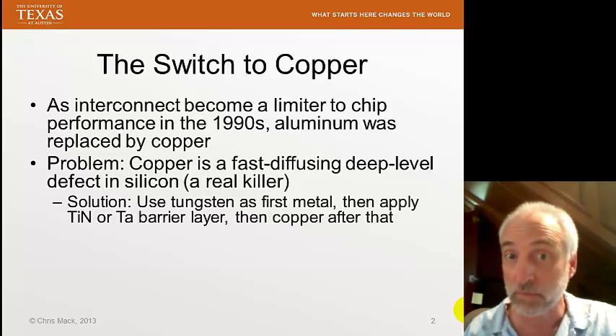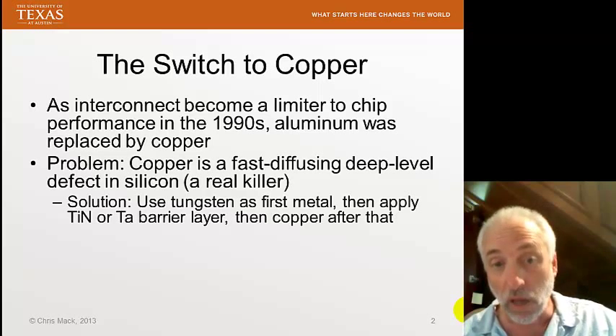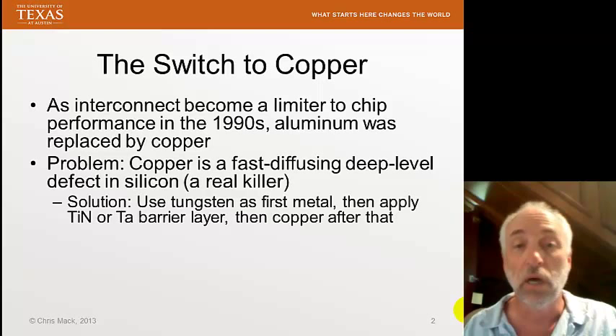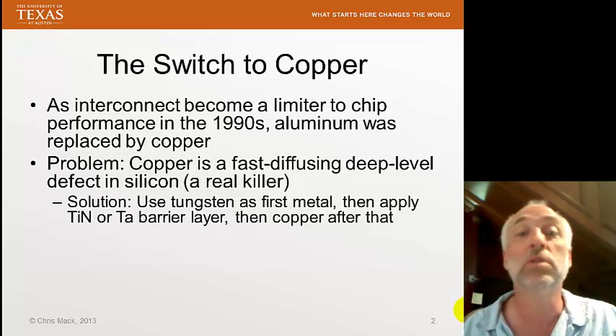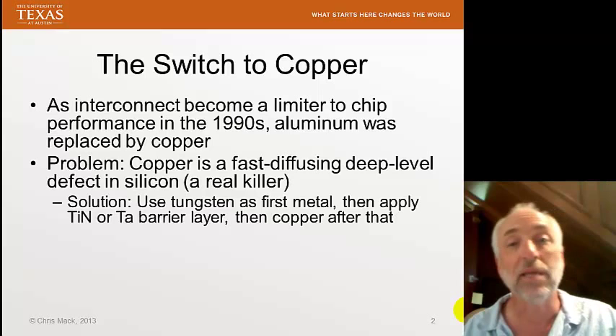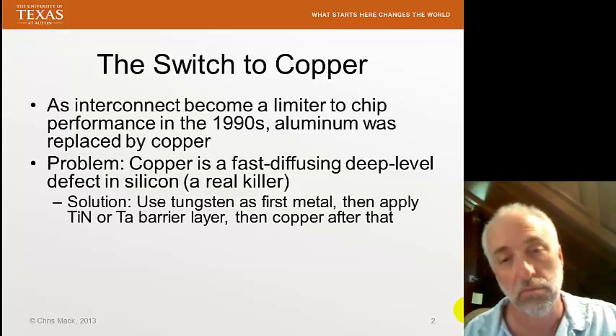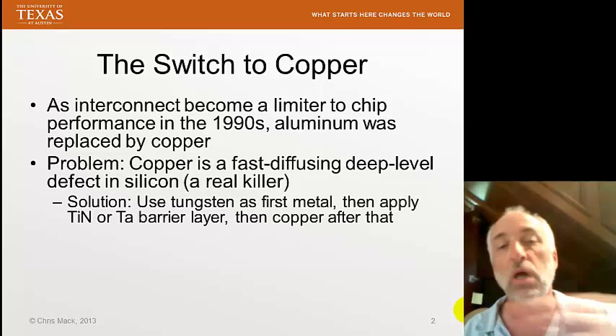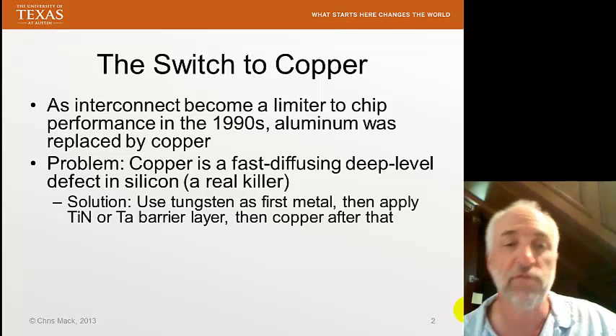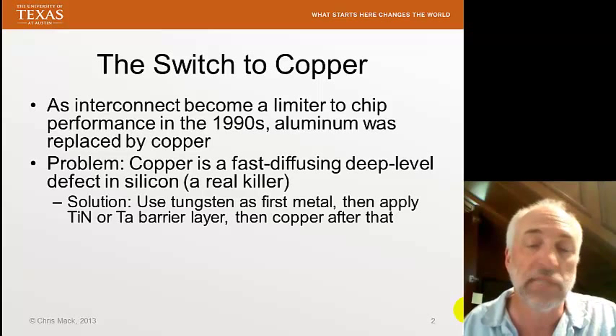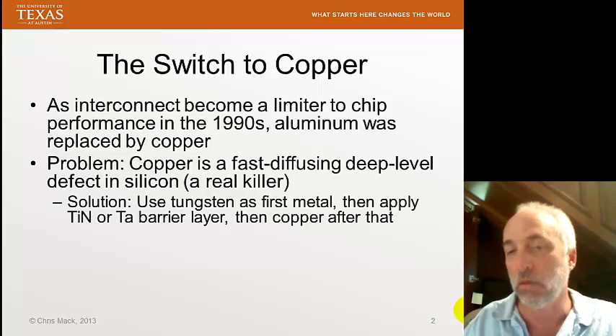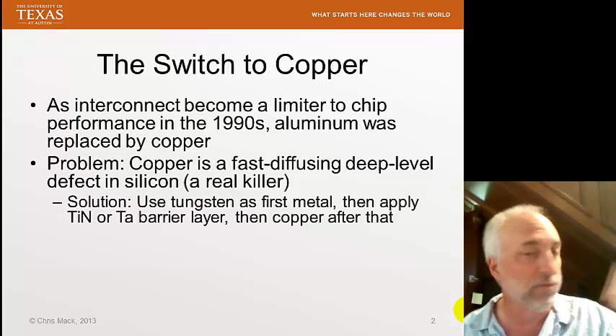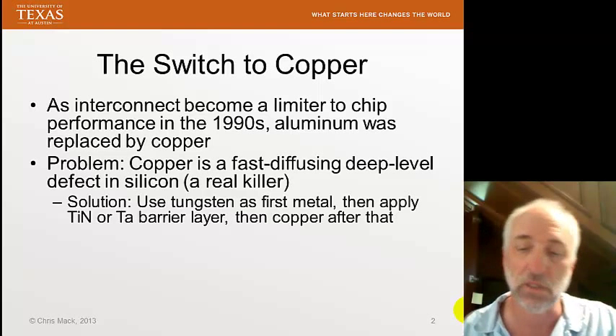It doesn't take a whole lot of copper to kill a transistor. Copper is fast diffusing, so once it gets anywhere in the silicon, it can easily move around and find its way to the critical areas of the device. Our solution is to put some other material to make contact with the silicon. We use tungsten as our first metal, and then we use copper to connect to the tungsten. We also seal the entire wafer with a barrier layer — titanium nitride, tantalum, sometimes silicon carbide — diffusion barriers so that copper can't diffuse down to the silicon interface.